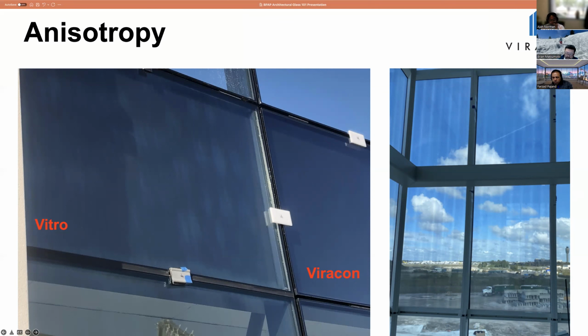Viracon, about 10 years ago, and it's actually probably longer than 10 years ago, when we did the Ronald Reagan Library with you guys, there was a structural glass wall, and I don't remember who supplied you guys that system, but the anisotropy was really bad, and from Viracon. And it was after that we invested millions of dollars retrofitting all of our tempering ovens and making sure that any new tempering ovens were set up the way we needed them set up to reduce the anisotropy.